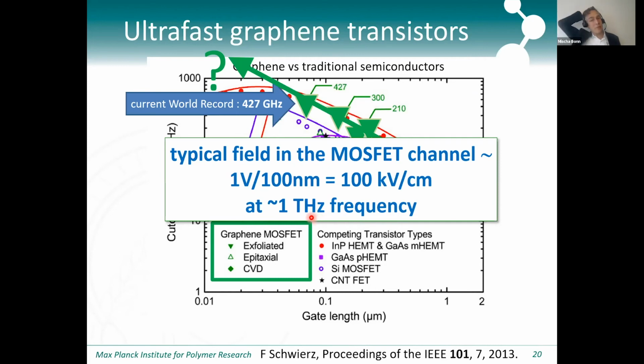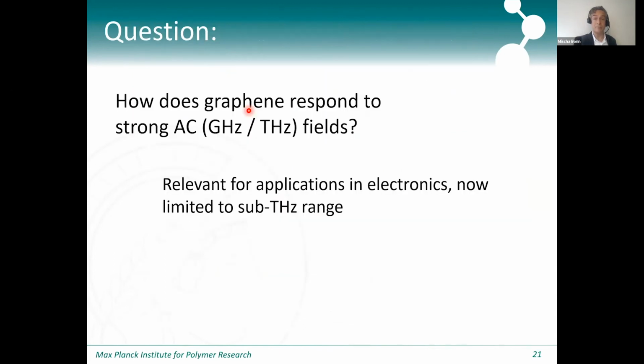And so this is something that we can look at, because 100 kilovolt per centimeter is a field strength that we can generate in our lab. It's not that difficult. And then we can see, is there some intrinsic problem with these high field strengths that become increasingly higher as you make the device smaller? And of course, the frequency also gets higher as you make the device smaller.